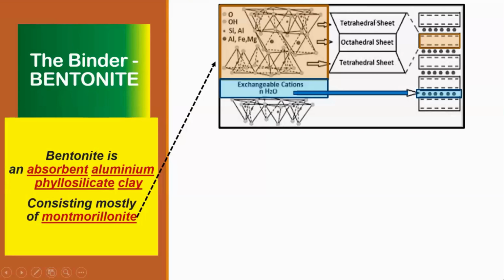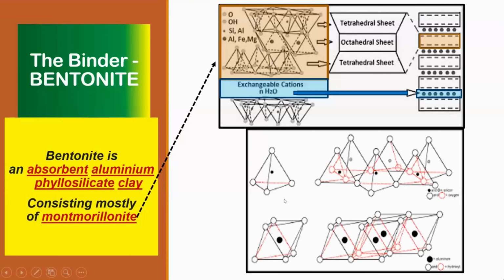montmorillonite. So one montmorillonite crystal will have a tetrahedral sheet of silica, an octahedral sheet of alumina, and again a tetrahedral sheet of silica. This is the general structure of montmorillonite. So each silica tetrahedron looks like this, and then a cluster of them in one layer. And then you have the aluminum octahedron in the second layer, and the third layer is again the silica. Now, between this and another montmorillonite, you have these exchangeable cations which are hydrated. The nH2O represents the hydration.